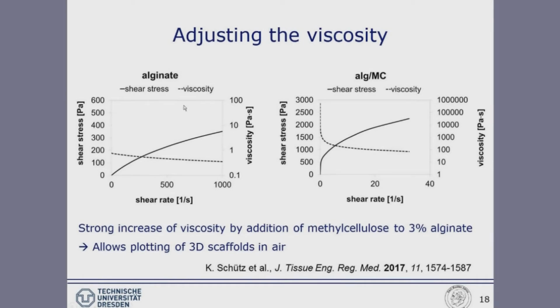So these are the values for pure alginate, shear stress and viscosity. Please look at the scale of this graph here in comparison to the blend, alginate-methylcellulose, where we have completely different values. And especially we have a very nice shear thinning behavior, which I'm sure you already have heard about, which is of course one of the relevant properties materials should have if you want to use them successfully in bioprinting. Due to time limitations, I will not go into details now.